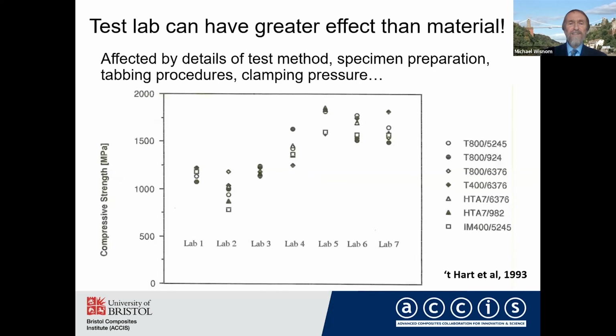However, if you replot that by lab rather than by material, you can see some definite trends. And in fact, the test lab, in this case, is having a greater effect than the material itself. And that's because the results are affected by details of the test method, specimen preparation, tabbing procedures, and other issues, clamping pressure, and other details of the test, which can have quite a big effect.